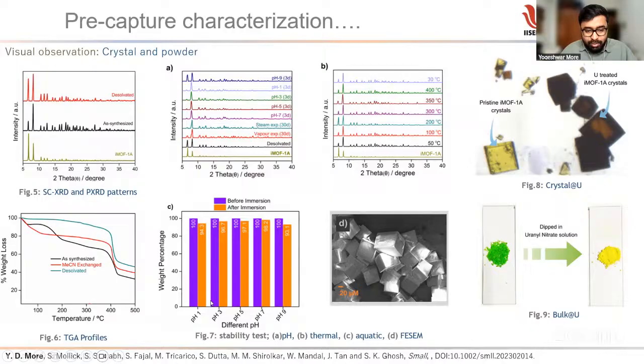We have done this for pH 3, pH 5, pH 7, pH 9, and finally we understood the leaching percent is negligible, and the MOF stability is considerably high, and it is quite high at pH 7, pH 5, even at pH 3 also.